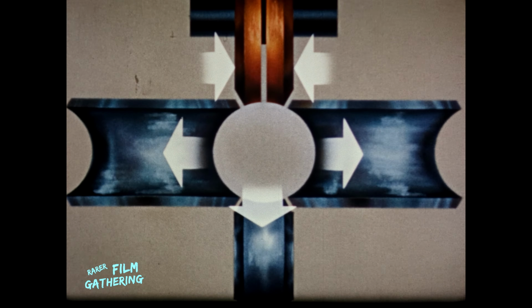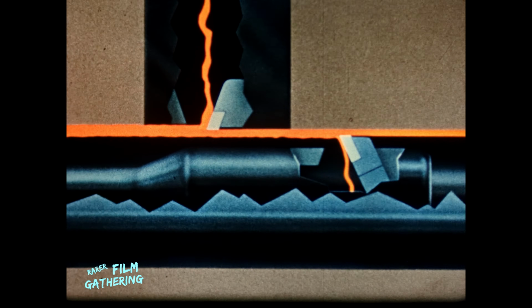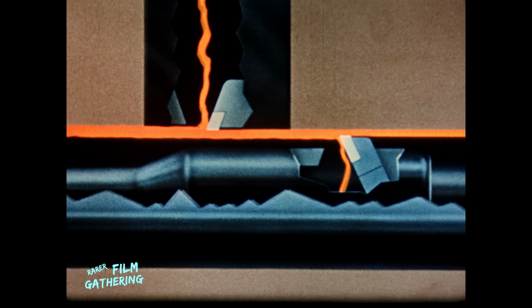There are 3 pressure rolls, all turning with the electrode. The open tube moves right into the welding machine, where the revolving electrodes contact the steel close to each edge. Careful coordination of speed, pressure, and current by means of an elaborate system of controls produces a metallic bond from the parent metal. Just enough is extruded inside and outside to give a uniformly strong weld. Stationary cutters remove the extruded metal and leave the wall thickness at the weld the same as at any other point. There you can see it. The metal is still plastic, and the stationary cutters are removing the extruded metal, leaving the wall thickness the same all the way around.